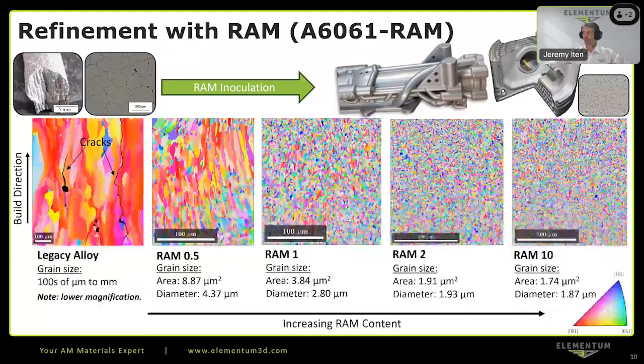Let me show you on this slide as well. There's a top right microstructure. The left is a non-RAM microstructure with the cracking. The very top right, that is a 10% volume fraction ceramic phase microstructure. And you can't see the scale on that. I apologize, it's quite small. But it almost looks a little bit like concrete, only on a much smaller scale, on a micron scale instead of a macro millimeter type scale.